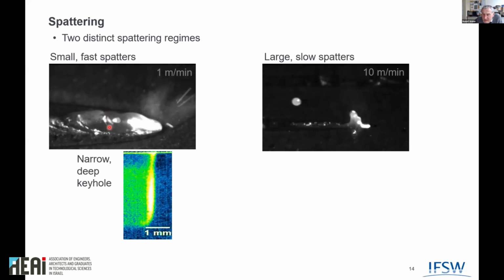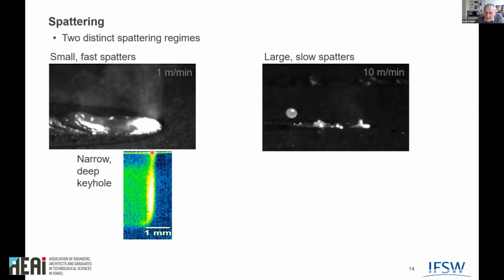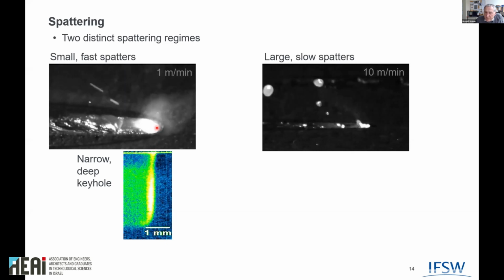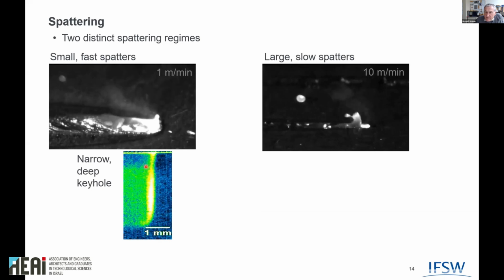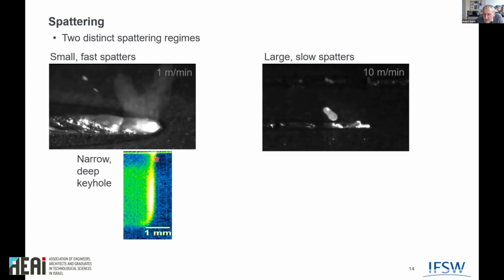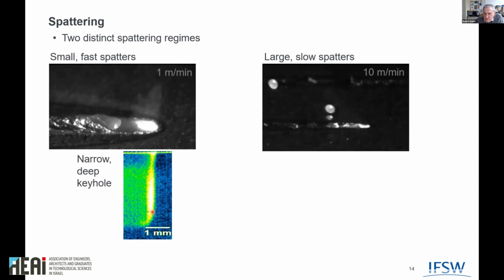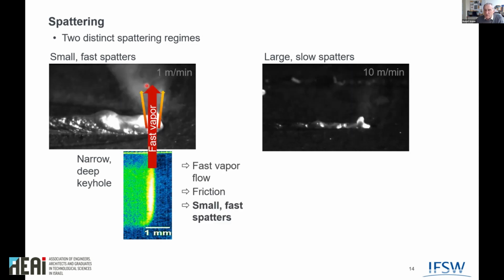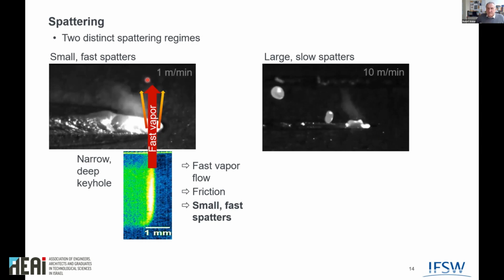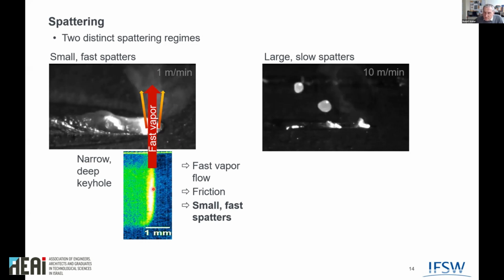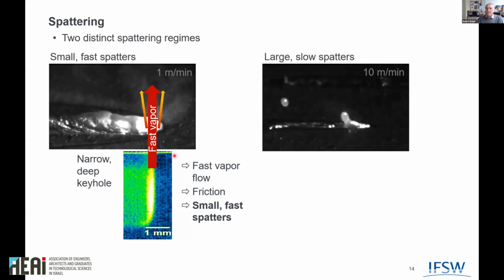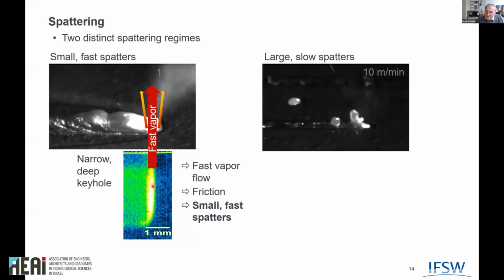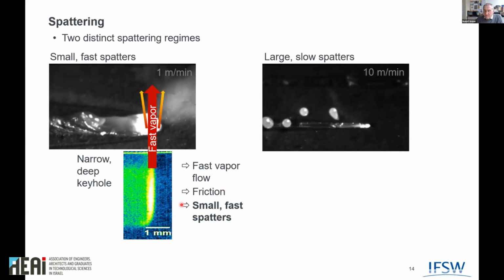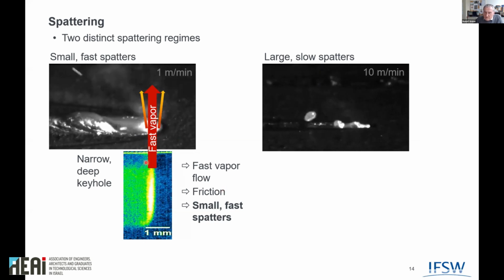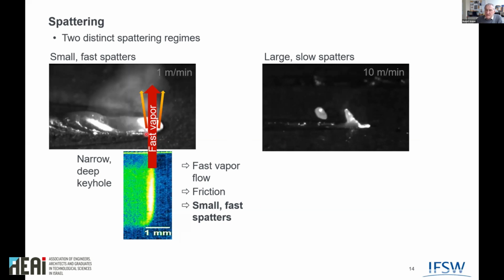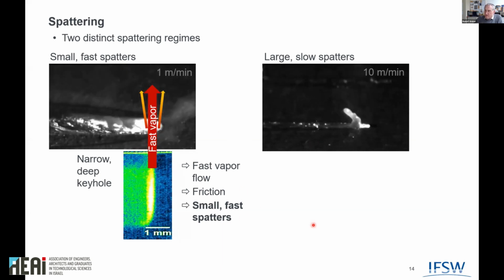So what happens? If you look at the X-ray again, now in false color, you see that in this case, we have a very deep and very narrow keyhole. If the keyhole is so narrow, this means that the vapor which is created down here by the laser has to emerge very fast. You all know Bernoulli's law, of course. If the cross-section is small, the vapor has to emerge very fast. This fast vapor causes friction on the surface and tears away very small droplets which originate from the surface inside the capillary. So in this case, we have a lot of small and fast spatters.